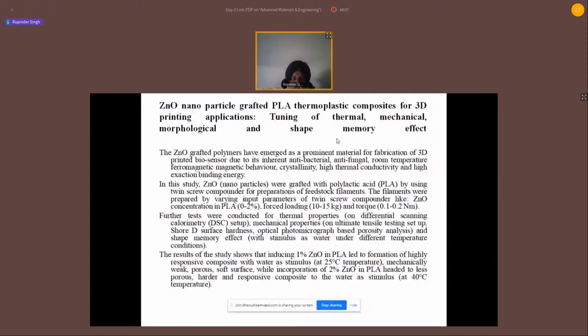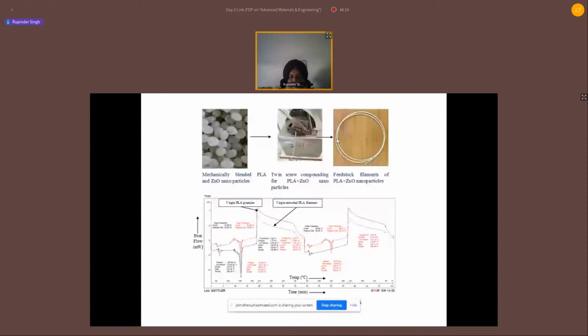In this particular case, we have put ZnO nanoparticles into PLA, and we tried to tune the thermal, mechanical, morphological, and shape memory properties. Now if you see stepwise over here, I have some thermoplastic granules of PLA, and ZnO nanoparticles were reinforced into it. So we prepared the feedstock filament.